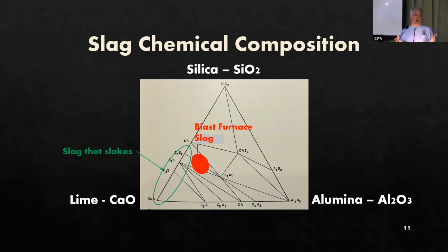By the early 20th century, scientists learned that they could chart these more complex relationships by using diagrams like this one, which is called a ternary diagram, where you're plotting the composition against 3 different axes. In the lower left-hand corner, that's 100% lime, calcium oxide. Lower right-hand corner is 100% aluminum trioxide. And then on the vertex of the triangle, you have 100% silica. If you had a material that was made up of equal amounts by weight of lime, silica, and alumina, it would plot in about the middle of that triangle.